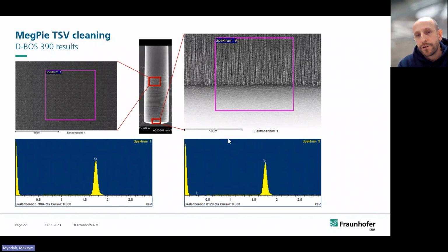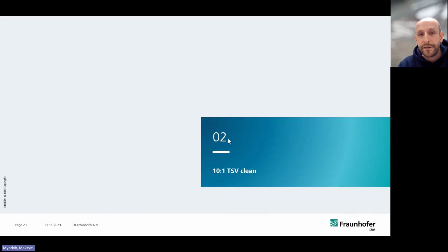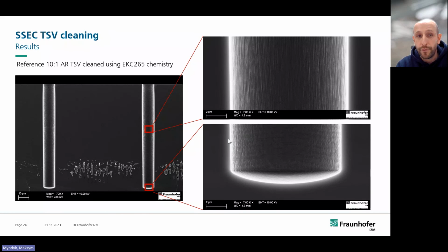But in-house, we still have another dimension of TSV. One of the dimensions that we very widely use is a 10:1 critical aspect ratio. The dimension of the TSV is 10:1, so a 10 micron opening and 100 microns deep etch. Here in this case, we have also performed the cleaning using the EKC chemistry. And after that, we will compare the results to D-BOS.